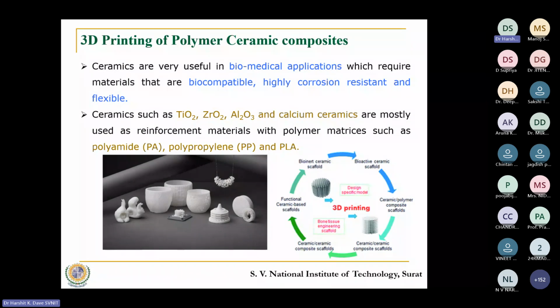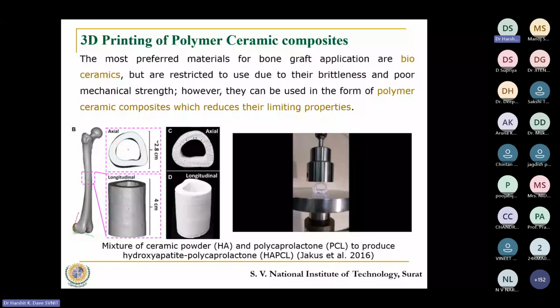People have reported some studies wherein they have tried to work with ceramic particles mixed with the polymers. So usually ceramics are very useful in biomedical applications, wherein we require biocompatible parts, very corrosion resistant parts, and at the same time we want them to be flexible. So certain ceramics like titanium oxide, zirconium oxide, aluminum oxide, and calcium ceramics have been reported to be used as reinforcement materials with different polymer matrices like polyamide, polypropylene, and PLA. These are biocompatible. So you can mix them in the right proportion and create parts. Usually people have attempted to create scaffolds so that they can mimic the original situation.